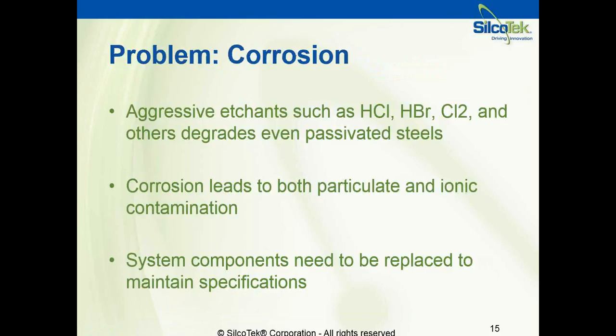Another very common problem that we deal with, not only in semiconductor applications, but all of the applications that we're involved with here at SilcoTek, is corrosion. So HCl, HBr, all kinds of corrosives that will degrade even a passive steel through interactions within the process stream. So of course, corrosion will lead to particulate generation. It'll cause the substrate to degrade and flake into the process, and those ions will get in there and harm the yields of the process later on down the line. And not to mention that these systems, when this happens, this leads to replacement, maintenance cycles, very costly implications of corrosion and the degradation of the equipment. So very high cost of ownership and system downtime, which over time is becoming an even bigger issue than it was in the past.